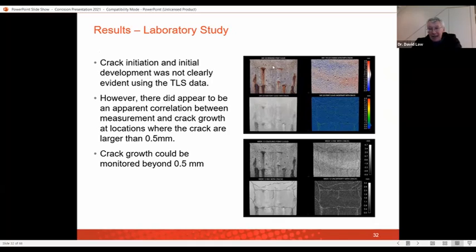And so you can see here, this is what it looked like in the lab, and then this is how we can enhance it using our laser scanner. What we did find is that we needed the cracks to get to about 0.5 millimeters before we could really follow them with the laser scanner. This is because the laser scanner was getting lost in those very small cracks and not being bounced back accurately enough to be able to see them. But once they got to 0.5, then we could produce these maps that we could see down here. And so this is a very good way of seeing where the cracks are, but we can then also monitor the crack growth over time using this technique.